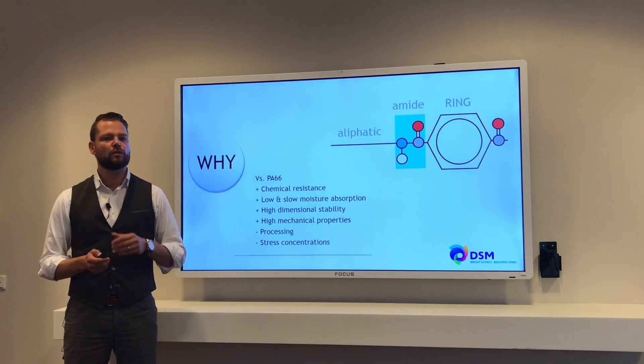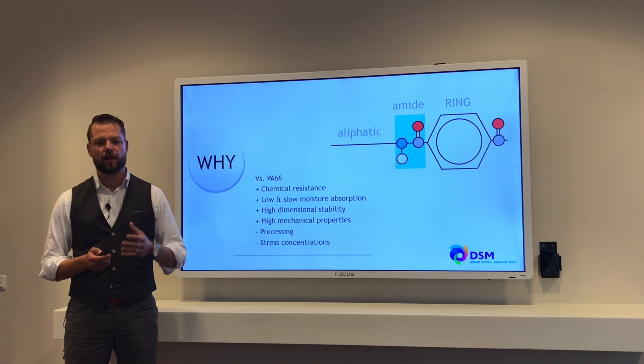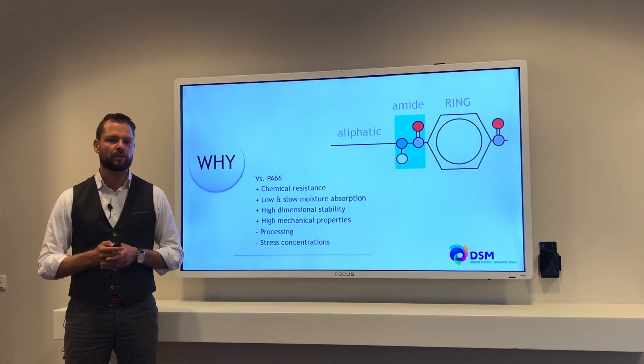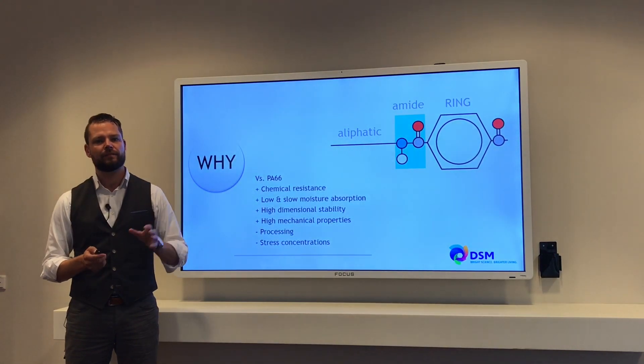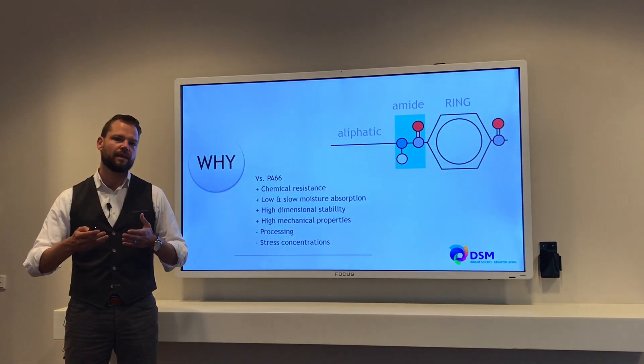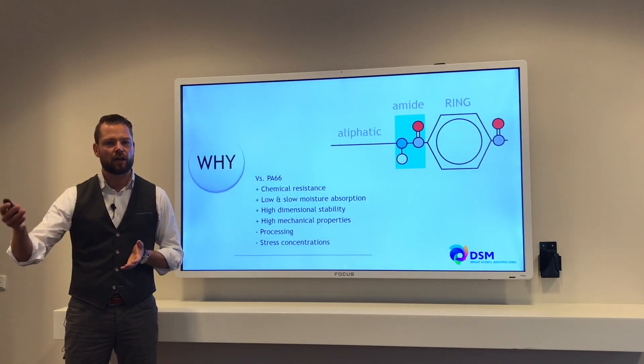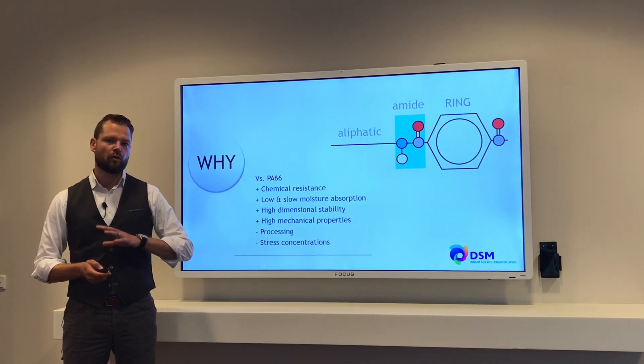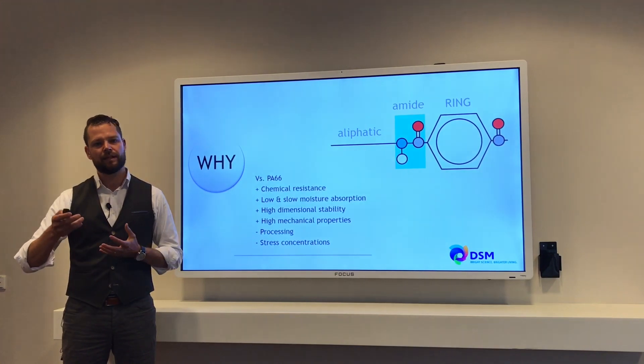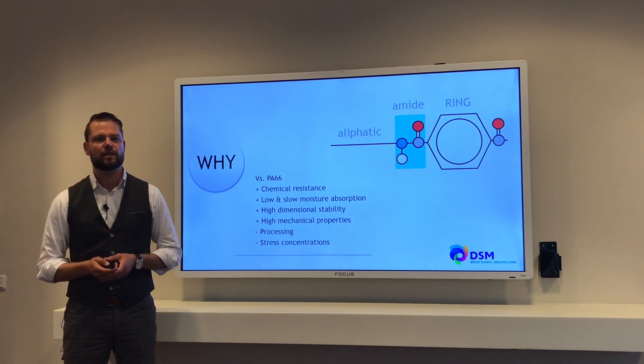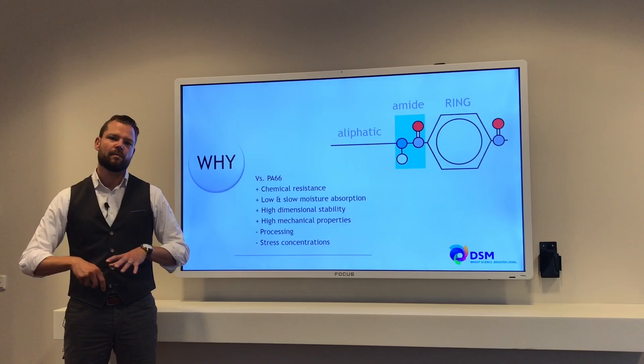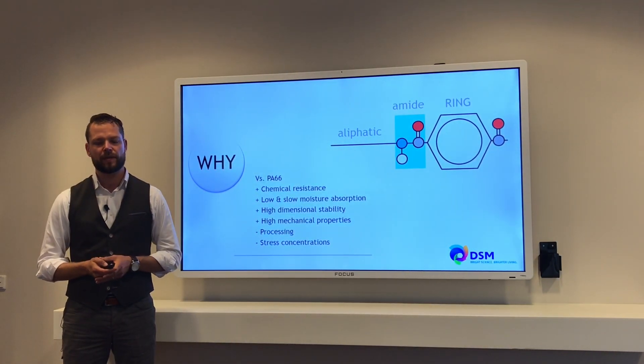Furthermore, due to that low and slow moisture absorption, it also has a very high dimensional stability and very good mechanical properties, especially at elevated temperature. This is because typically PPAs have a higher glass transition temperature than the aliphatic ones, the polyamide 6-6. Often processing and dealing with difficult stress concentrations was seen as a drawback, but that's something you do not see anymore in the latest generations of PPAs.